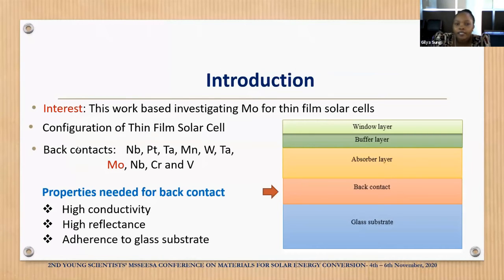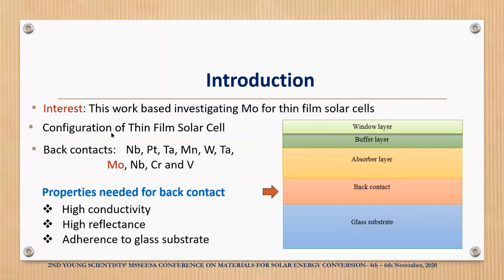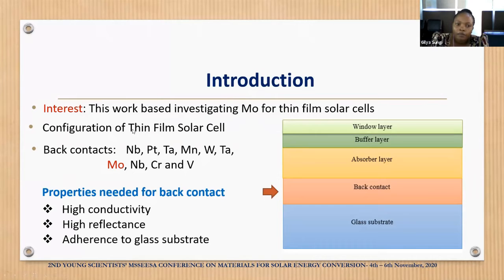The interest of this work is based on investigating molybdenum film for thin film solar cells, which can be fabricated using the configuration shown, which comprises 4 layers: back contact, absorber layer, buffer layer, and window layer. Basically there is a material and a method used to deposit each layer. But the focus of this discussion will be on the back contact, whereby a lot has been done and different materials have been suggested to be used as back contact, for example niobium, platinum, and molybdenum.